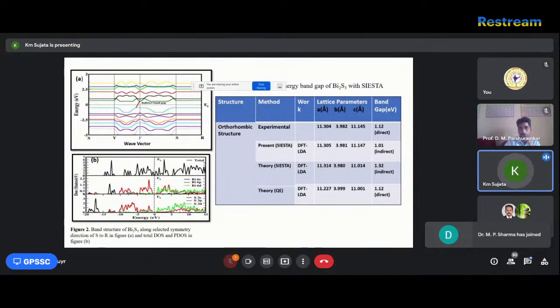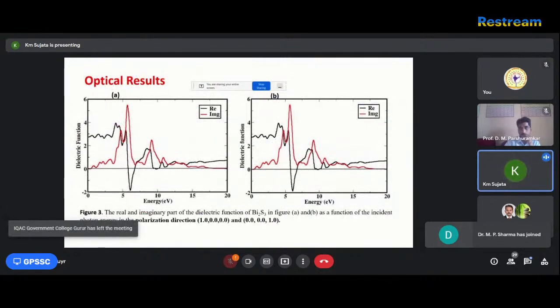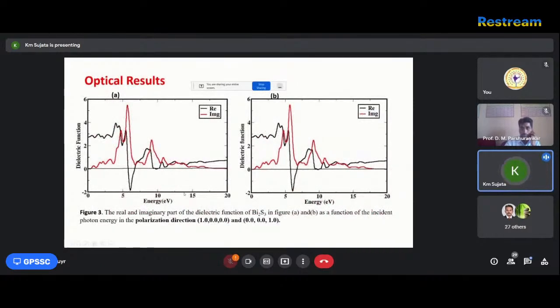This is the optical results, the real and imaginary part of the dielectric function of bismuth sulfide in the X direction and in the Z direction. Now the dielectric function of the material is examined in order to evaluate its optical properties. The complex dielectric function is made up of two components, real and imaginary part.